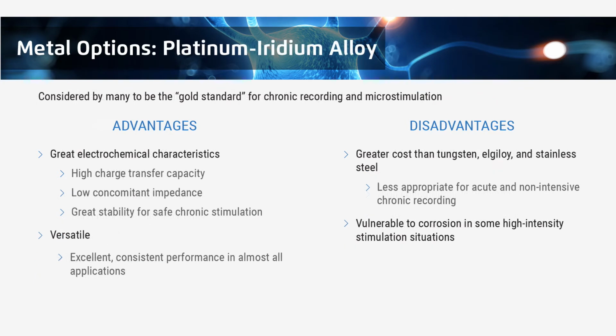The second metal option is platinum iridium alloy. Platinum iridium is becoming the gold standard for many for chronic recording and microstimulation, mainly because it has great electrochemical characteristics compared to tungsten, particularly its electrochemical stability. Platinum iridium is much more noble, has a high charge transfer capacity and low concomitant impedance, which means that it's excellent for stimulation. It's also very versatile. It gives consistent performance in pretty much all applications.